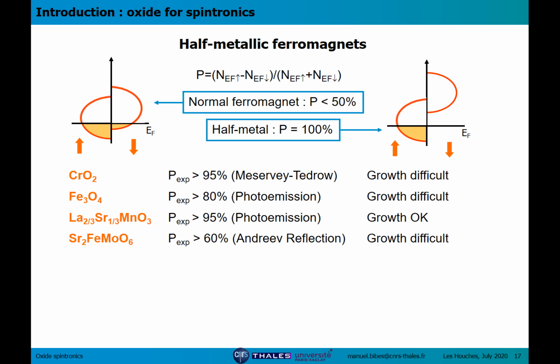And these double perovskites, strontium iron molybdenum oxide, became popular at the end of the 90s after a very important paper by the group of Kobayashi and Tokura. There's a whole family of these double perovskites. Several are predicted to be half metallic, and the advantage is that they have quite high TC, higher than LSMO, higher than other perovskites. They can reach maybe 600 or 700 degrees. They are relatively difficult to grow as well, and there are some reports of relatively high spin polarization.